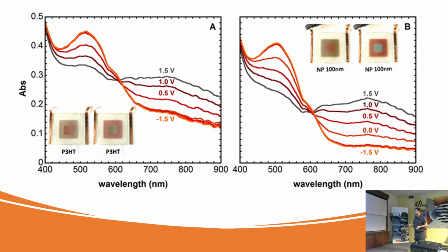And yes, these photos just show that the contrast is really big. In here, I hope the video appears, as it is a little bit upside down, but it's okay. These are the thin films, these are the nanoparticles. You can see already the intensity of the color, and the switching is much faster when you have the nanoparticles. Okay? So, again, another color change. And so you have this color change that are extremely fast with nanoparticles and much slower with the thin films.